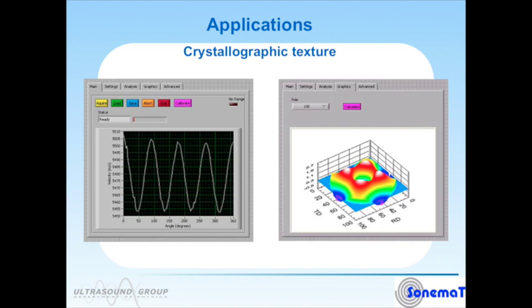Locked within there is quantitative information about the material property, and we can use it to generate figures such as that shown on the right, which are effectively equivalent to a kind of X-ray pole figure, which is what would typically be used in industry. But to take an X-ray pole figure measurement, you'd have to cut up a small sample, use lots of sample preparation, and then do a long exposure experiment on the sample. Total sample preparation time would be several hours. Total experiment time might be over an hour.